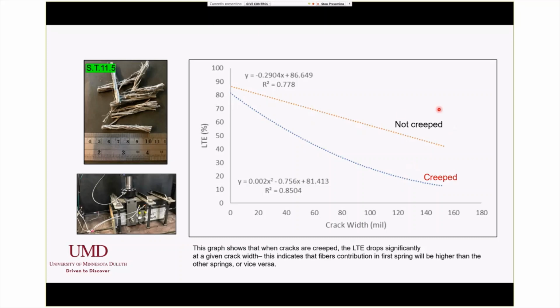We also had some beams which were not creeped. You can see the load transfer efficiency was 20 to 30% or even more higher than those beams which were creeped. So this is another thing we probably need to look at. This particular finding tells us that